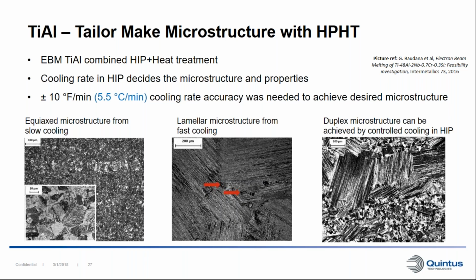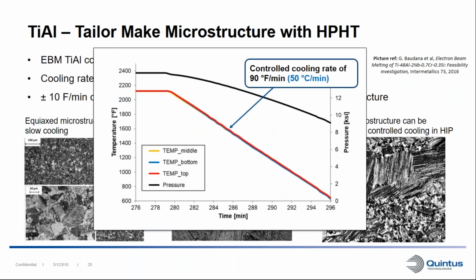And to get exactly the desired microstructure in this case, we had to have a very good accuracy of our cooling rate to set the exact microstructure. So we had to be actually within plus minus 10 Fahrenheit per minute in cooling rate. And here's just an example how we can actually achieve that in a HIP system today, where we program 90 Fahrenheit per minute, and that's exactly what we get.